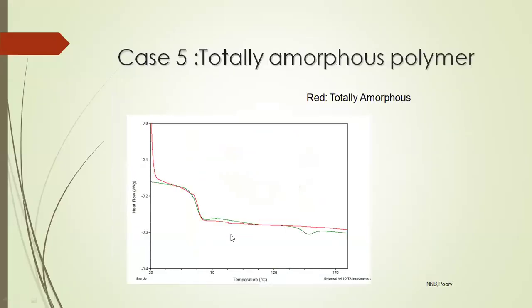Again, many times you get material from your manufacturer and you think it is pure, totally amorphous. But if you do a DSC and you build a heating curve, then it shows a totally amorphous polymer. But many times you get a small melting in your polymer, which shows that it is not totally amorphous. Just by doing one DSC, you can find out whether your material is totally amorphous or not, whether your material is aged or not.